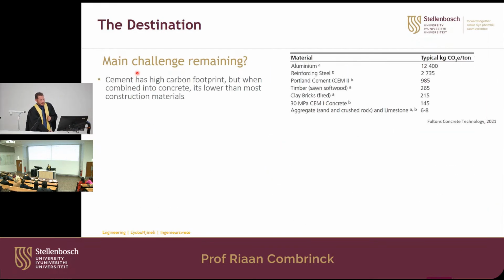Okay, but cement has a high carbon footprint if you produce cement. But when you combine it as concrete, in other words, once you add stone and sand to it, it's lower than most construction materials. So if you look at this table, you can see aluminium and reinforcing steel is up there with 12,000, close to 3,000 CO2 equivalent produced per ton of material produced. So CO2 equivalent emitted per ton produced.